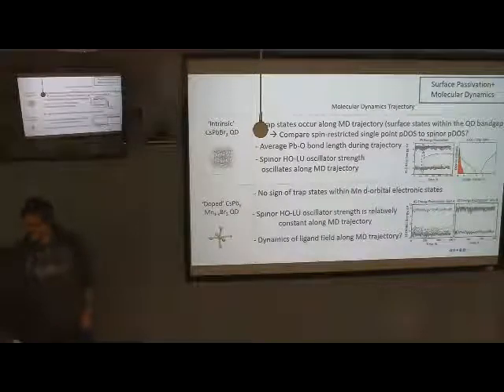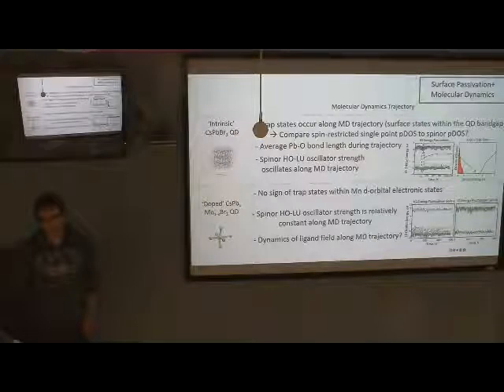But you can actually do it in between, like you can do it for each pair of atoms, wherever they interact, wherever the nearest atoms you have. So you can do this procedure wherever you have lead-bromine bonds, and see what you get. In other words, you can get the spectra for any nearest neighboring atoms, which give you some idea of the normal modes. Some of them might be really harmonic, some even non-harmonicity will be present through this method, which gives you the whole spectra of the vibrations you have for the system.